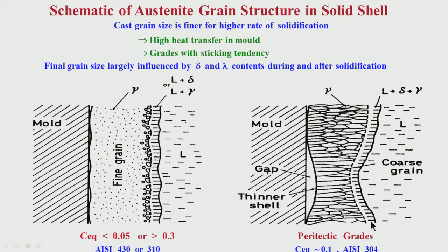But for the so called peritectic grades, that means chemistry near the start of the peritectic chemistry, around 0.1 or around 0.55 nickel equivalent by chromium equivalent for stainless steels, you have depressions. Because of that there is a gap formation, we call it hot spot formation. Because of that heat transfer is affected, becomes low, and we have coarse grain structure.